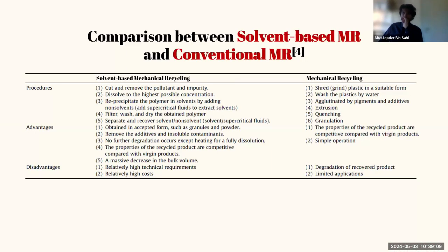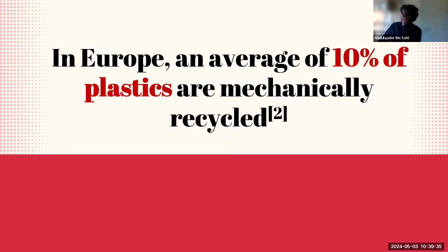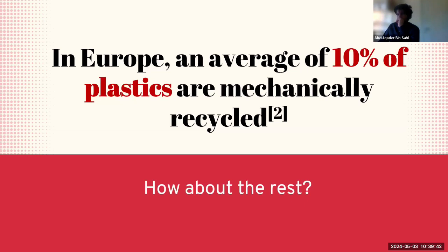So just a quick comparison between solvent-based mechanical recycling and conventional mechanical recycling. We can see here from the advantages and disadvantages that solvent-based mechanical recycling is good. However, it has relatively high technical requirements and relatively high cost, whereas mechanical recycling is much cheaper, but of course, it comes with its own limitations. In Europe, an average of 10% of plastics are mechanically recycled. So what happens to the rest, or why only 10%? Well, this is because mechanical recycling requires plastics to be pure and free from contaminants to be effectively recycled. So this restricts the application to a narrow range of plastic waste, leaving out many commonly used plastics.